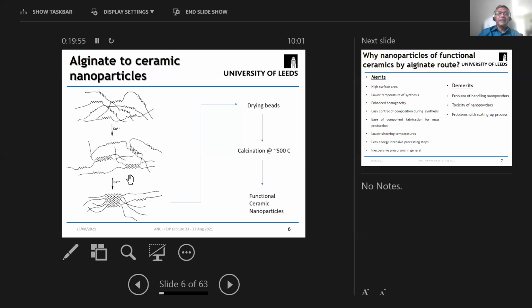So we produced the beads and we dried the beads. You can dry it either by freeze drying or by a normal convection oven process, whatever you have. And then calcine the beads at about 500 degrees Celsius. Now, interestingly, the calcination temperature does not change dramatically if you change the material itself. So from one material to another material, which I'll show you in a minute, it still remains the same, which is a mystery. Why it remains the same is still not very clearly understood. And once you calcine these dried beads, you get functional nanopowders of the cation that you have ion exchanged. So oxides basically. You can't get any nitrides or carbides, or oxynitrides, but you can get oxides very easily.